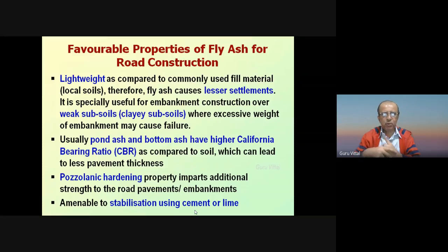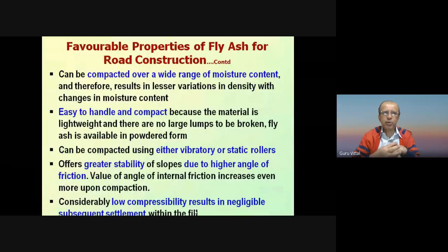It is amenable to stabilization using cement and lime, this point I just told. It can be compacted over a wide range of moisture content, and therefore results in a lesser variation in density with changes in moisture content.